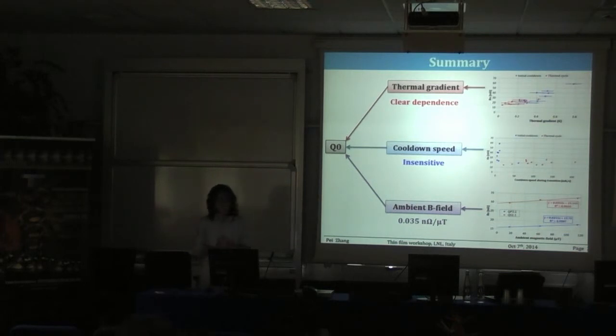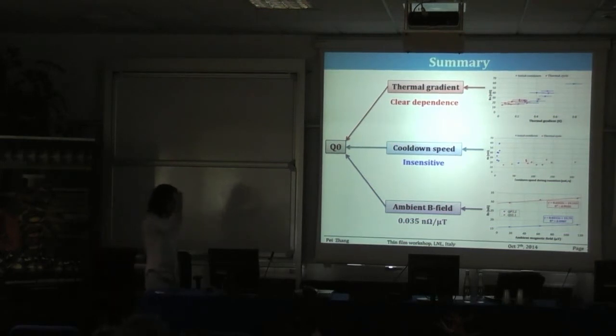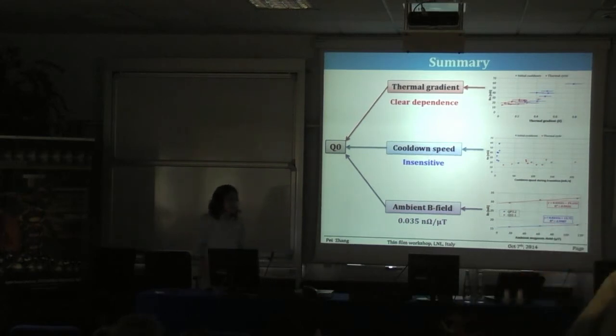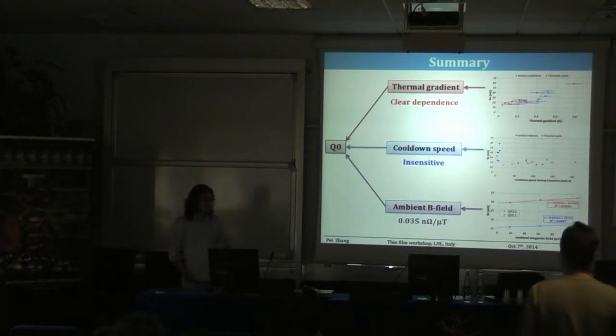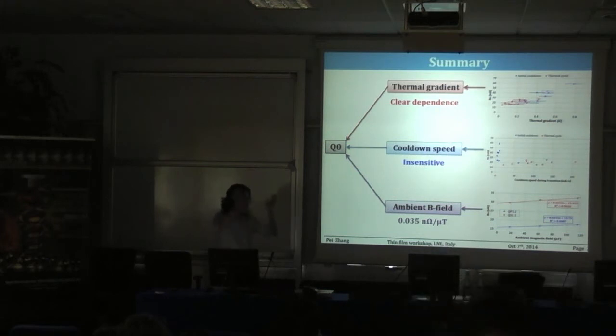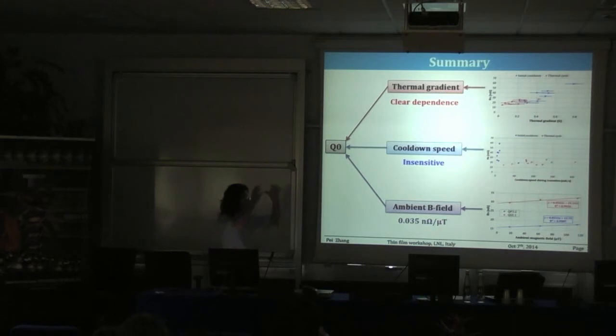Question: How do you perform the thermal cycle exactly? Answer: We stop the helium flow so no helium goes into the cavity, and the cavity warms up. To accelerate this, we turn on the RF to boil out all the helium inside the inner conductor. After that, we let the cavity warm up, keeping it inside the cold box so the thermal screen is still cold. The cavity warms up to about 15K, then we start the helium again and the cavity cools down.